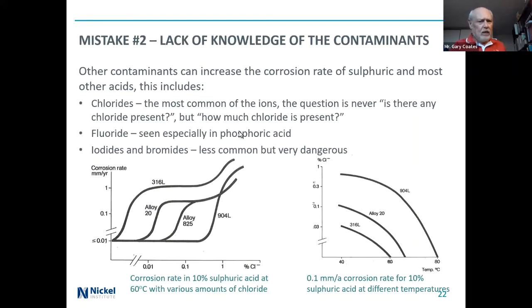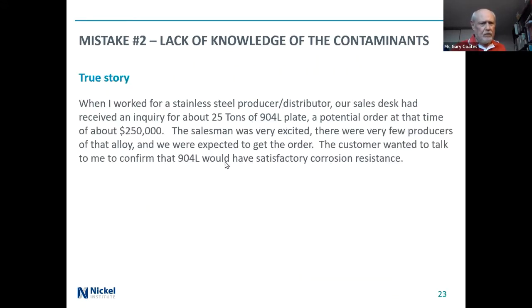Fluoride is also very dangerous, increasing the corrosion rates. We see it a lot in phosphoric acid and it is one of the key contaminants to increase corrosion rate. Very important to know the fluoride content in the phosphoric acid. And iodides and bromides, they're less common, but also very dangerous as contaminants.